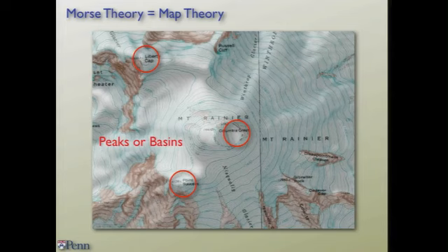And you say, well, Maurice mentioned that when you have systems with translational order, you can't have any kind of defects you like. There's some extra integrability condition. So let me think about it. Here's a +1, here's a +1. Suppose I try to add the two +1s together by bringing them closer to each other, which you can do in a nematic. People do it all the time. They bring the point defects together. You get a +2 defect. You can bring 3 of them together. You get a +3 defect.